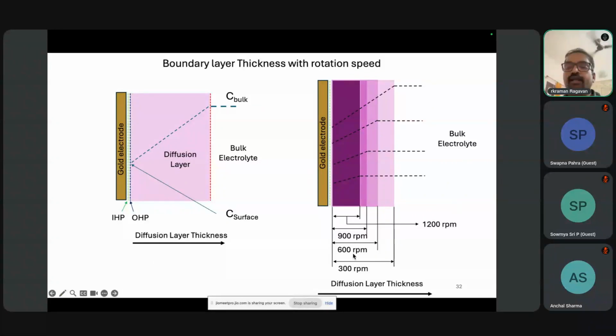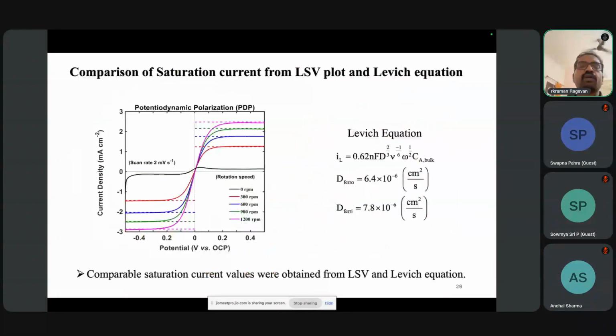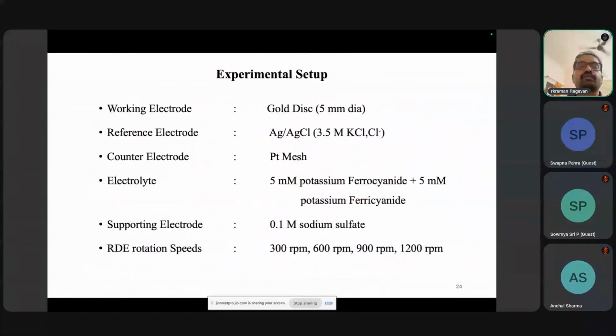Therefore, at different rotation rates, for example at 300 RPM, this is the thickness of my diffusion layer. If I go to 600 RPM, it will decrease further. If I go to 900 RPM, it will decrease further. If I go to 1200 RPM, it can decrease further. So a big diffusion layer can be made very thin by simply rotating the electrode. That means a semi-infinite problem can be turned into a finite problem by doing a rotating disk electrode experiment. So that is what we are going to do now.